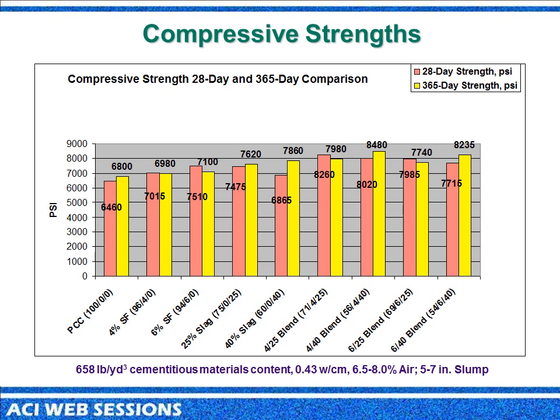Now, many of you are probably asking, why did we choose 4 and 6% on our silica fume? We have a very large pavement program in Michigan as well as in Ohio. The Michigan DOT will go up to 6% silica fume, and the Ohio DOT will sometimes use 4% silica fume. So we try to use representative averages of materials that would be allowable by the DOT. However, I will also state that being very close to a blend that's at 4/40 is very difficult and quite a challenge to also move through the DOT as well.